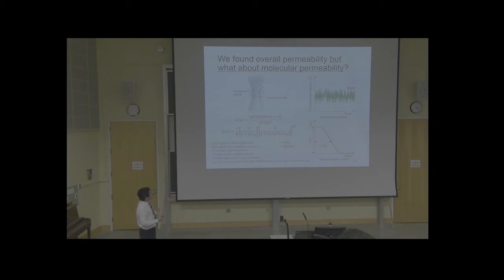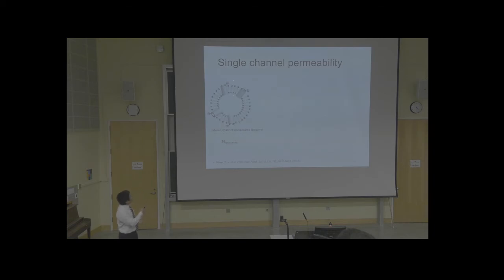So based on this information, we designed this experiment. First, because our channel has a carboxylic group at the end, we can easily tag a fluorophore on the channel, so it becomes fluorescent, and then we incorporate it into a vesicle. If you see, it's one single fluorescent particle, but made of four channels, right? And then we test the fluorescent intensity, and then we get the autocorrelation function. We get the number of liposomes in that small volume. Then we solubilized this vesicle in a detergent solution.